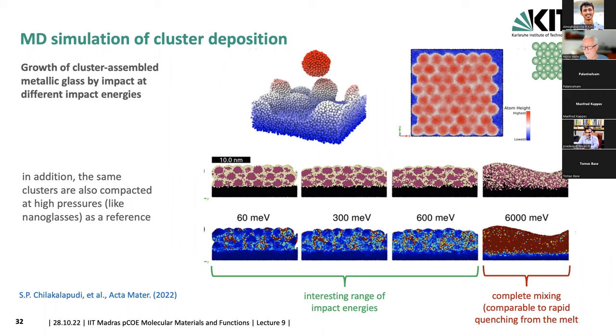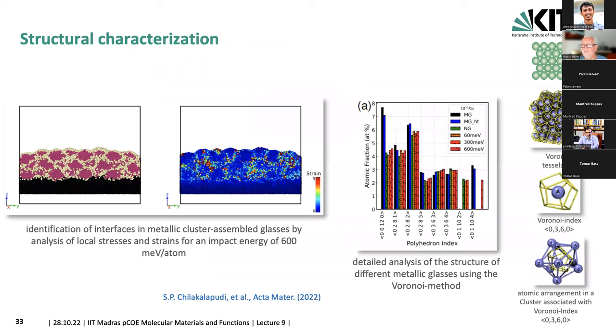And then you can further analyze it, and there's a whole literature on that. You typically use the Voronoi tessellation, and you have Voronoi indices, which are shown here on the right side, in order to describe the local atomic arrangement, which you can then plot in atomic fraction for these different Voronoi indices. And from that, and the comparison to metallic glasses, which are rapidly quenched, you can see the subtle differences. And the differences are really only subtle in terms of what you achieve at the low impact energy or high impact energy. But still, these small differences seem to be important also for these changes of, for example, the magnetic properties of these deposited films.